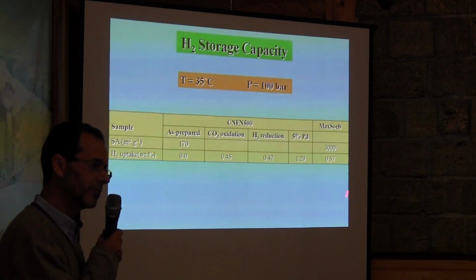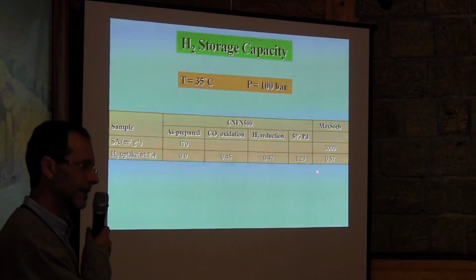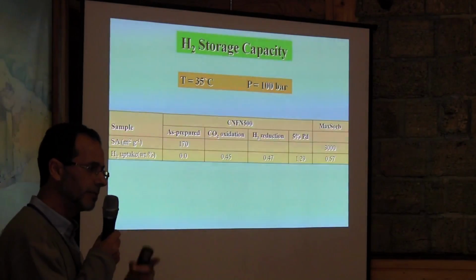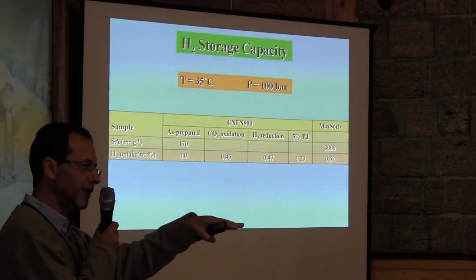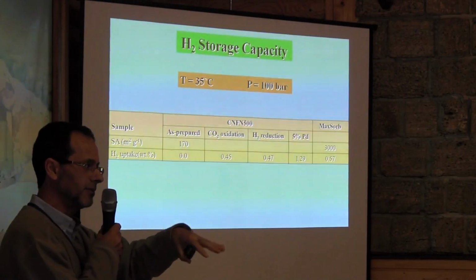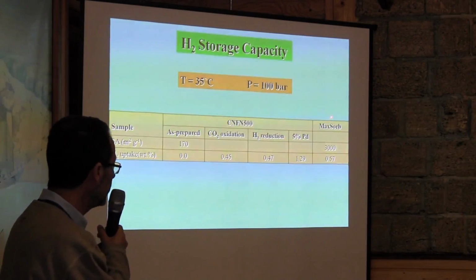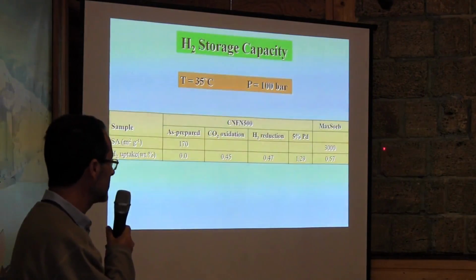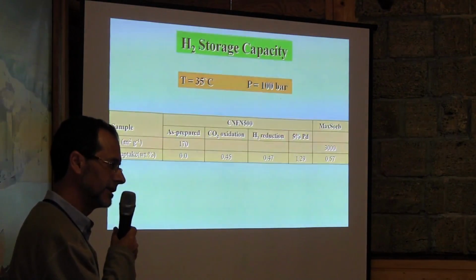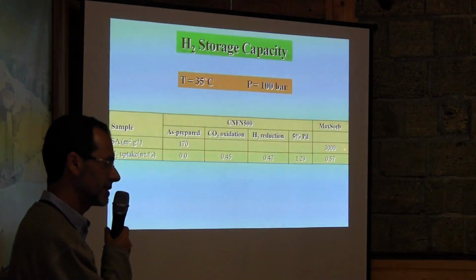Now what we did was decorate the carbon nanofibers with 5% of palladium, and we can reach 1.29, okay? Why? Palladium, as you remember, for thin films we also put a layer of palladium. It's very catalytic for hydrogen. Then we compare with MaxSorb. MaxSorb is a very well-known carbon material, and it has a very high surface area.